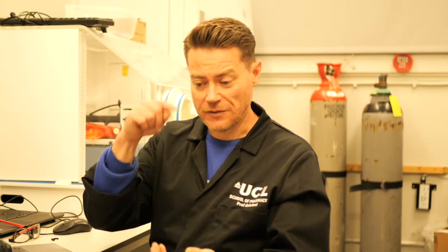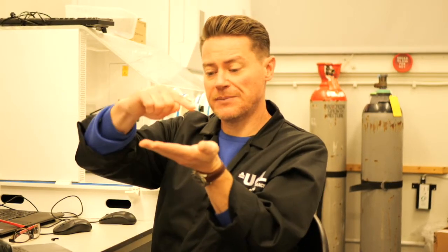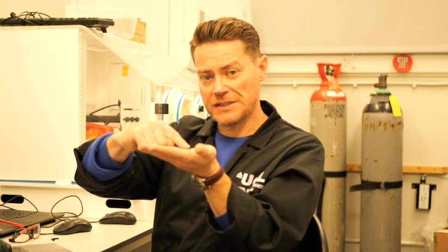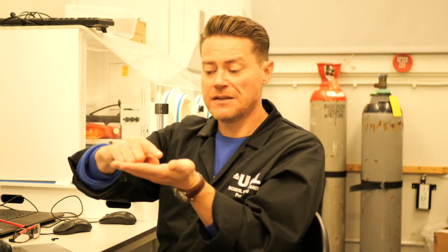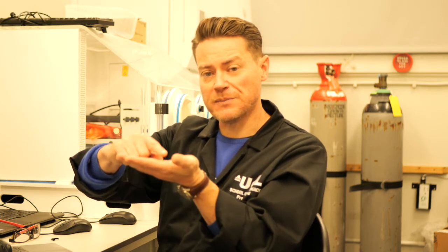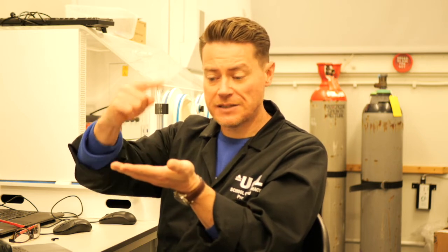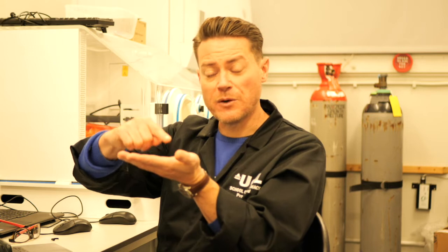You can increase the temperature of the AFM tip by putting more and more current through it. And what that allows you to do is to make almost like a DSC measurement, you can mimic the temperature profile of a DSC while you're making a measurement at the surface of your material. So imagine this is your material, the tip comes down, you can place that tip on the surface of the material and measure its Z position, but then you can increase the temperature of this tip, and what that will mean is if you increase the temperature but you haven't gone above the melting point of the material that's underneath it, the tip will remain in place. But as the tip temperature goes above the melting point of this material, it will melt, and as it melts the tip falls into the material. So by measuring the Z position and measuring the temperature, you can actually measure the melting point of the material that's underneath the AFM tip.